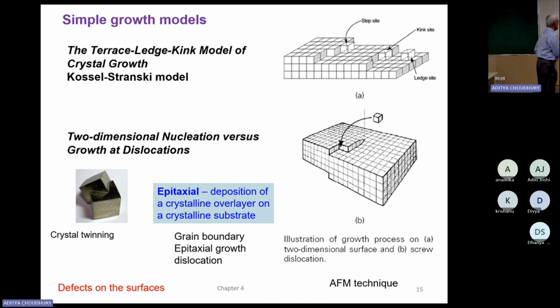When the crystal started growing, there's no way we can force it to grow on planar surfaces equally. One side started growing, the other side is not. Slowly, it started growing as a cube. There's a kink site, and this is a highly reactive surface, energy wise. This is very active, so it will allow the growth in this region. And then that forms some kind of steps. You always get a step and a ledge here. More and more nuclei will collide and deposit, and then crystals start growing in one direction. If you see some of the surface of the crystal using the AFM technique, you can clearly see the formation of these step-like growths.